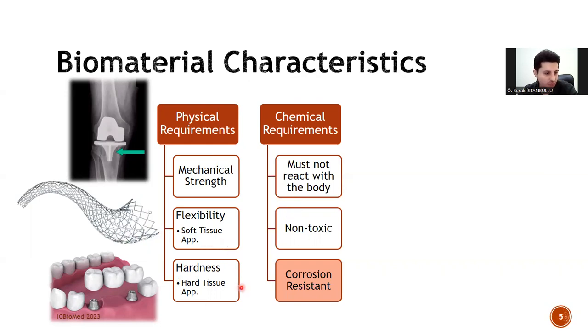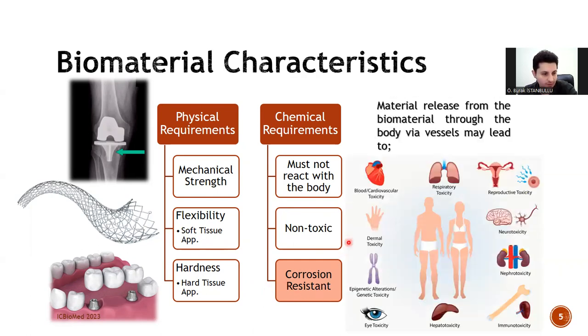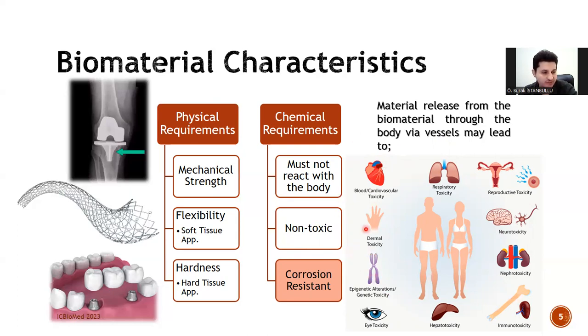To achieve these requirements, corrosion resistance is also expected from biomaterials. This is very essential since, in case a biomaterial corrodes in the human body, it can lead to toxic effects even though the whole structure is non-toxic. This is due to the fact that materials released based on the corrosion mechanism are very small particles that can travel through vessels into any tissues near or far from the implant, potentially leading to toxic effects in any organ in the body, as shown in the schematic diagram here.